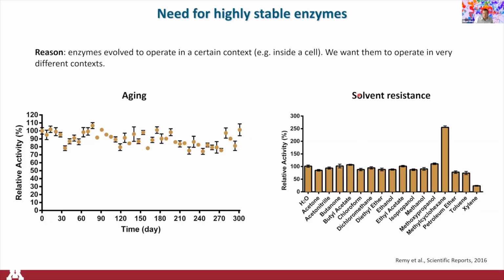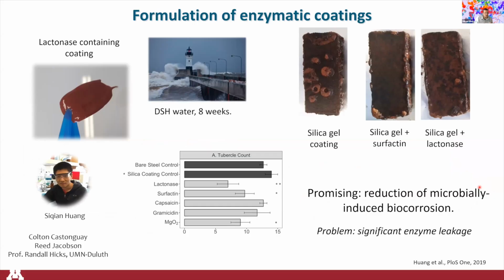And they can also resist fairly well quite a variety of different solvents, right? So you see that the starting activity here, everything is normalized. So 100% is the activity in water. And you can see that in all of these different solvents, the activity is about 100%. So no significant damage there. Here it's higher in this solvent. And for some of them, like xylene, it's lower. But mostly those enzymes are fairly solvent resistant, which is a good news if we want to include them into materials such as coating. So very desirable trait.